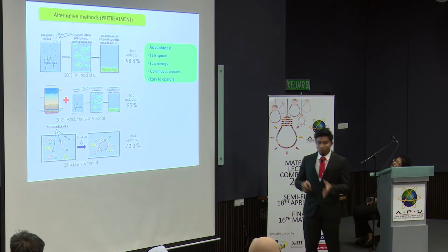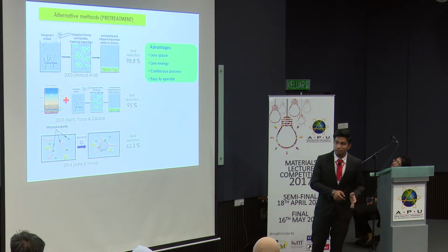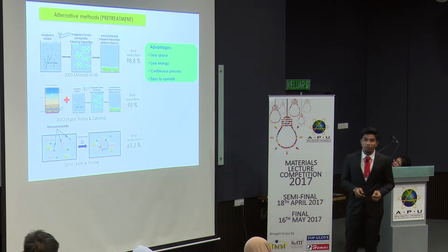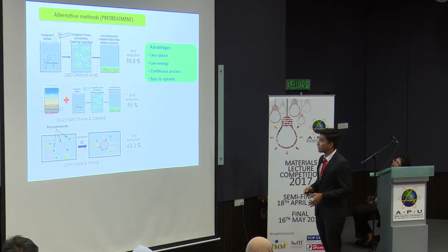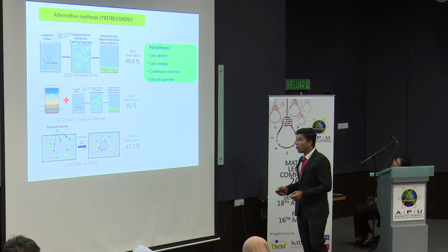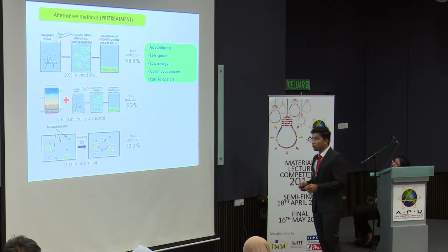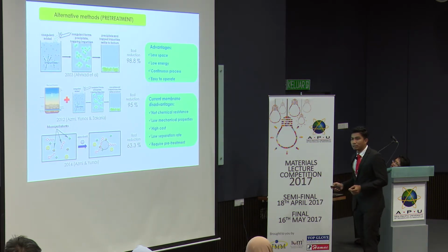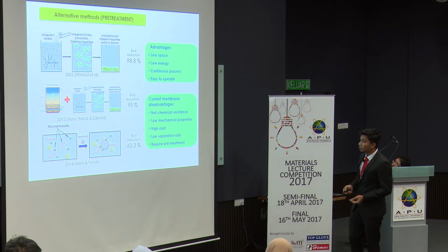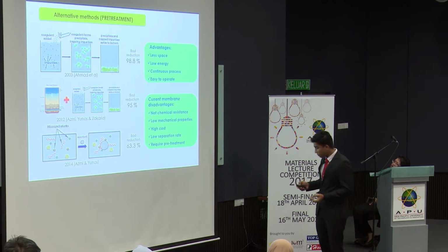The advantage of using this alternative method, that is the membrane method, compared to the conventional method, is that the membrane method requires very little space, is low in energy, is a continuous process and is easy to operate. However, some of the commercial membranes right now have limitations in which they are not chemical resistant, they have low mechanical properties, they are high cost, and they have a low separation rate, thus they require all this pre-treatment.